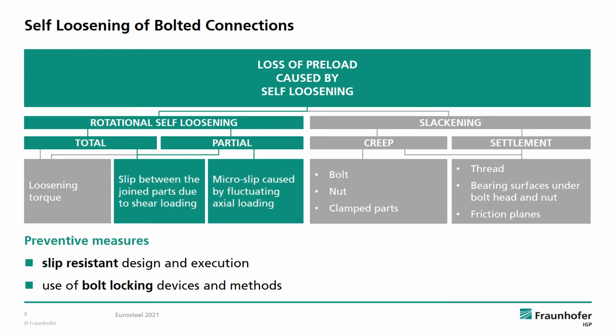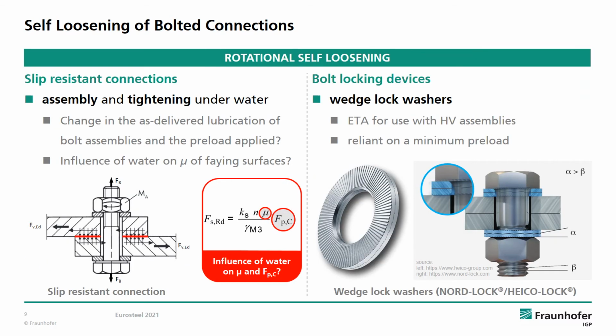Rotational self-loosening can either be partial or total, and there are multiple reasons for rotational self-loosening to happen. Most obvious, a loosening torque could be applied. Also, axial and especially shear loading can lead to slip between the joint components, which can ultimately result in bolts turning loose. This can be prevented by designing and executing bolted joints as slip-resistant connections or the use of bolt locking devices and methods. As our boat landing bolts are exposed to cyclic loading in multiple directions, designing them as slip-resistant connections was certainly right.